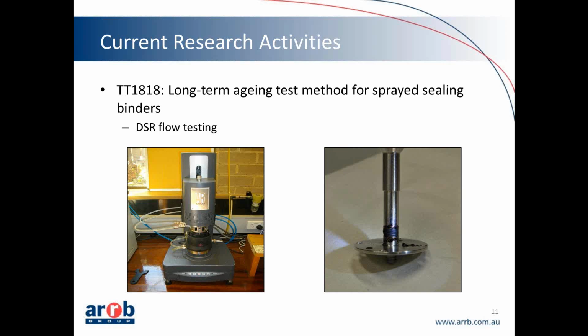And Shannon, how long does it typically take to run a DSR test? It's a good question, Angela. It depends on the type of testing that we're doing. For this particular project, a standard test would take roughly 2 hours before we got a result. Contact time, preparing the sample, things like that, is roughly only half an hour, 40 minutes. But you can vary that significantly. We can do different strains, frequencies, and temperatures depending on what's required and what information we want to get out of it. So yeah, that's that one.